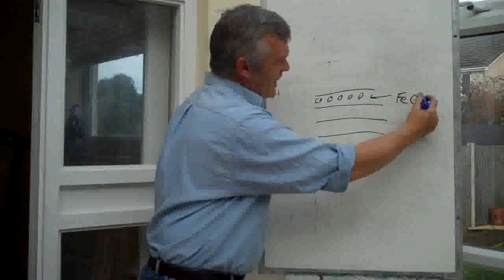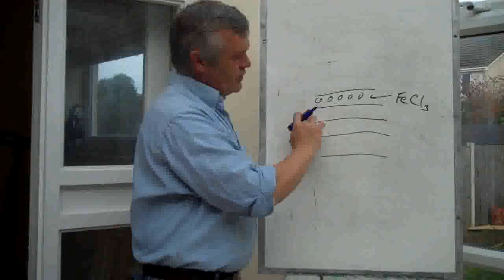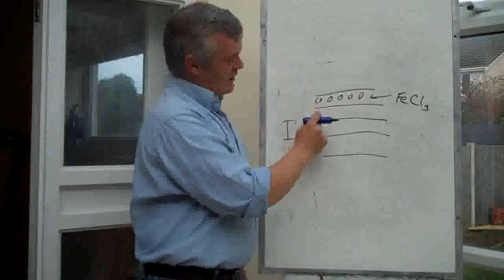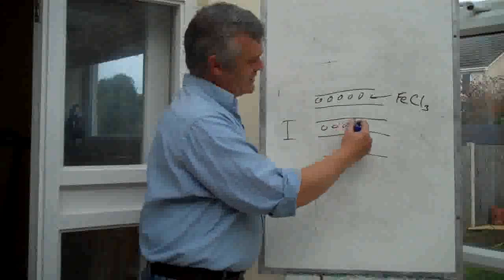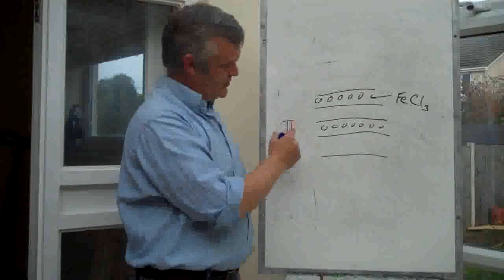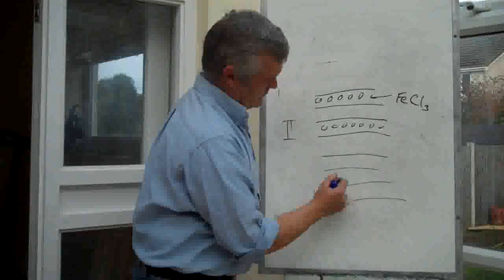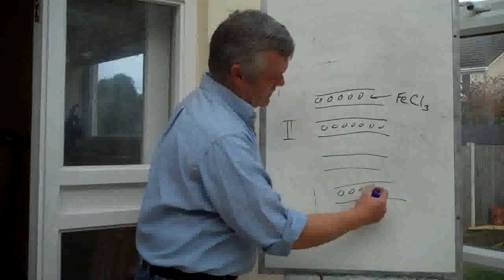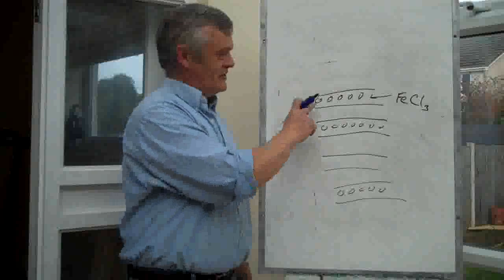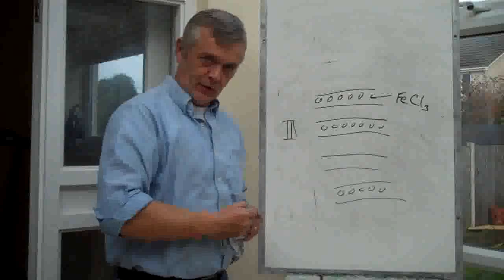What we're going to do is iron chloride — ferric chloride — we're going to force it in there. If it's between each layer, then it's what we call a stage one. If we have a layer with nothing in it and then on the next layer we have our intercalation compound, we get a stage two. If we have three layers and force it in there, we get a stage three. So the stage of intercalation compounds relates to the number of layers in between that don't have an intercalation compound.